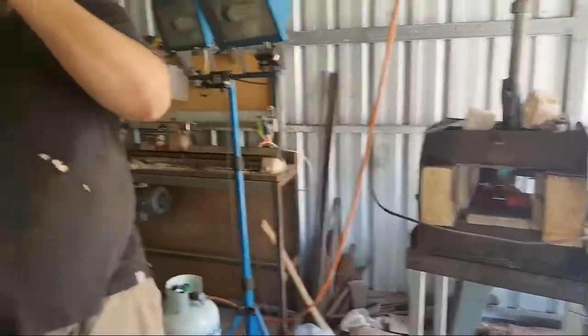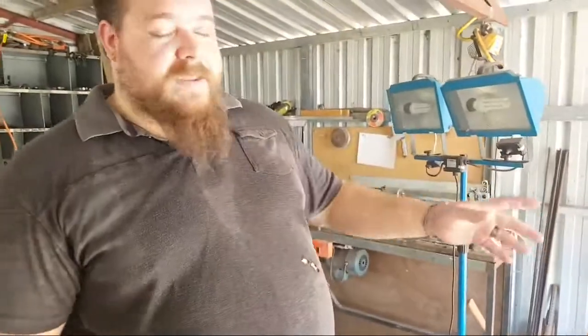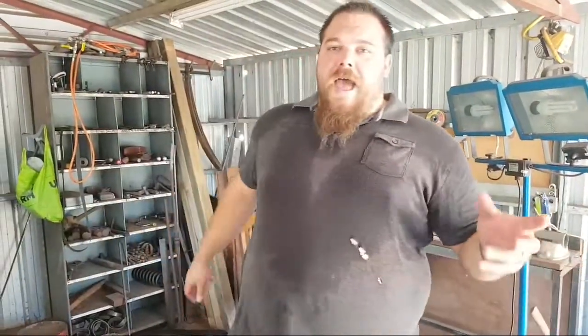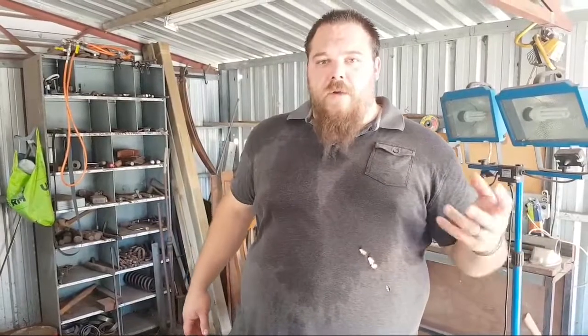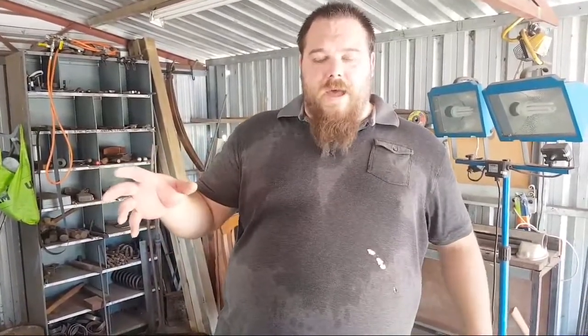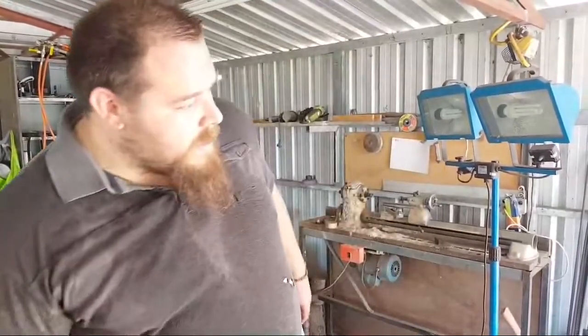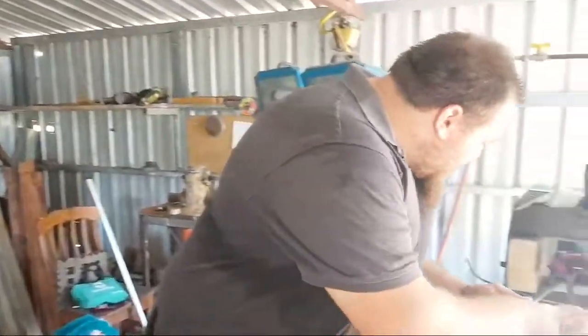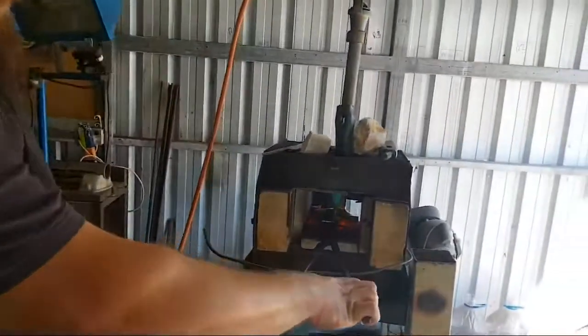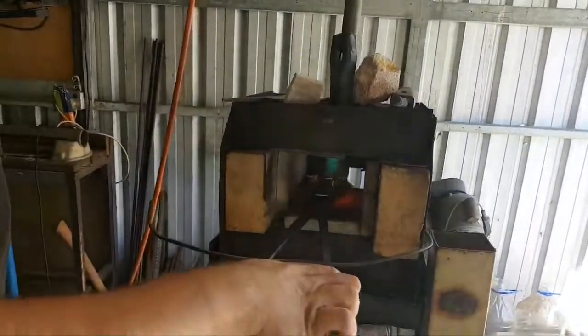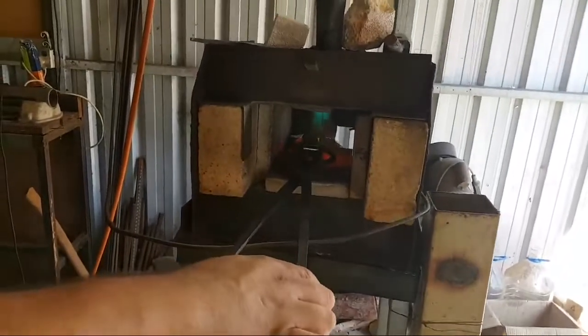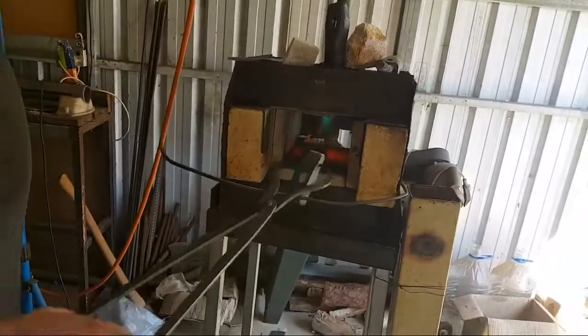A good way to test that is if you're heating your piece of steel up in your gas forge, and it gets to a point where you think it's hot enough to create temper colors, but it's not coloring, like it's still silver in the forge, and the moment you pull it out it temper colors, that means that you're running a nice rich flame. Like, I'm wondering if this is hot enough yet. You can see it's still silver in the forge right now, it hasn't changed color. The moment I remove it, nope, not quite yet.